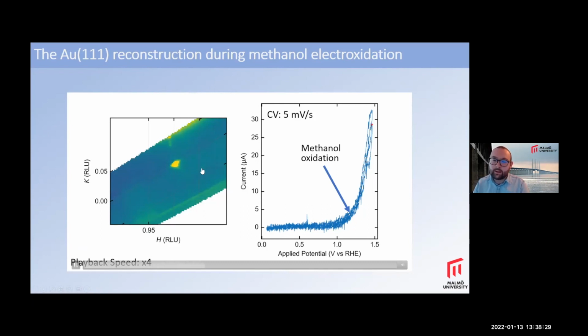methanol oxidation. So it's kind of interesting to know that if you do a first cycle into methanol oxidation, you really do still have the reconstruction, I don't know, quite far into it. And then when you reverse the potential, it's also interesting to note that you have to go to a much more negative potential to reform the reconstruction. And we're scanning quite slow here. We're scanning at 5 millivolts per second. So ordinarily it would have plenty of time to have recovered by now.